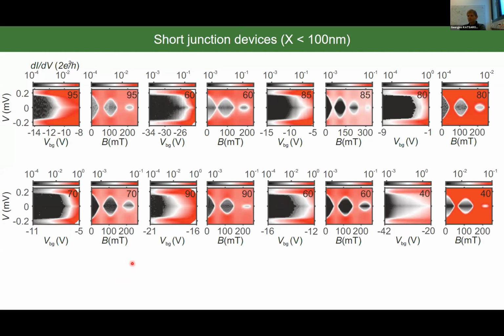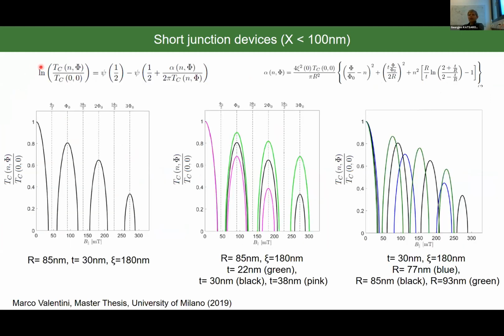If you take a careful look at these plots, you will see that there is a slight difference between the measurements. So for example, the height of the lobes is slightly different. Also, the distance of the lobes is a bit different. So how can we understand that? Going back to Landau-Ginzburg, there is a theoretical formula which allows us to extract the ratio between the critical temperature for each lobe versus the flux, where psi is the digamma function and alpha is the pair breaking parameter, which relates to the coherence length, to the radius of the nanowire, and the thickness of the superconducting shell.